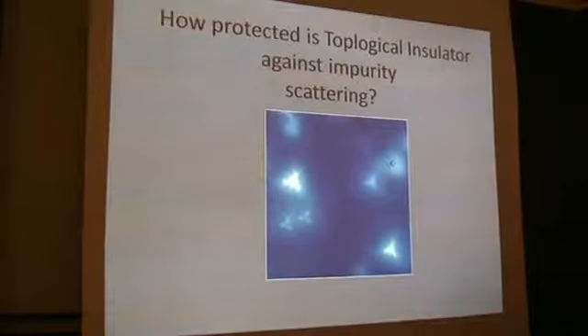I see no evidence for the protection. Bound states, if they appear, have to appear at an energy scale of the order of the bulk gap. No, it's not. That's the whole point actually. If I have an impurity strong enough, with U, with the spectrum way outside of this protected Dirac cone, my U could be an electron volt. My impurity resonance is generated at the energy scale of 1 over U, but nevertheless it inherently talks to the states outside of the Dirac cone.